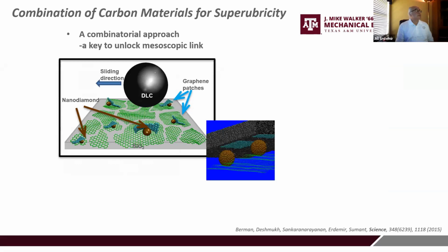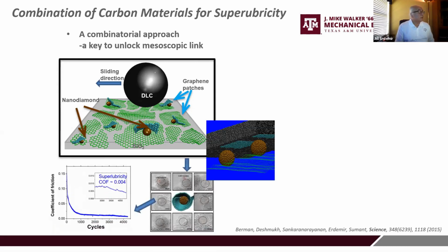In further studies, we have also seen that one can achieve superlubricity with graphene. These were discrete flakes of graphene sprinkled on a surface, combined with nanodiamond particles, typically 3 to 5 nanometers, rubbed against a DLC-coated ball. So we had carbon material in different forms - solid carbon on the ball side, plus graphene and nanodiamond. These combined carbon structures were able to bring the friction coefficient down to the 0.004 level.